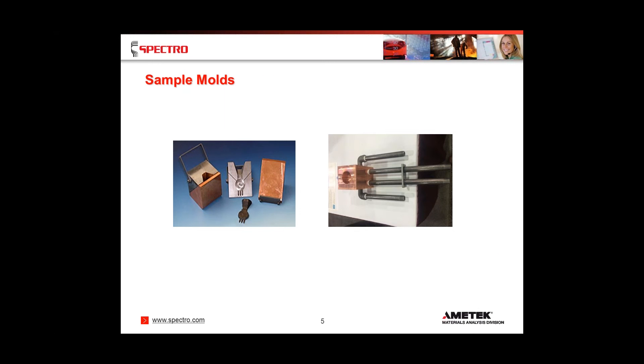Sample molds are going to be very important. On the left picture here, you see a solid copper block copper mold, made specifically for cast iron. It can be bought on the open market. It does not use water cooling — it's just a big basic heat sink that chills the sample surface very quickly. The one on the right is another big copper mold that is poured into, but this one has the ability to be water cooled. Of course, having water in a melting area could be a problem. So that's your options out there that you can look at for sample molds.